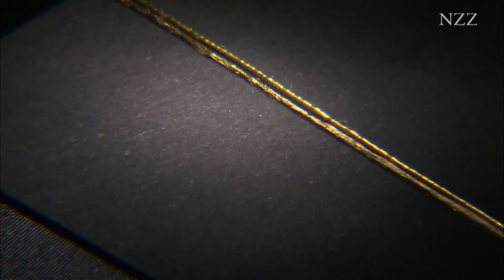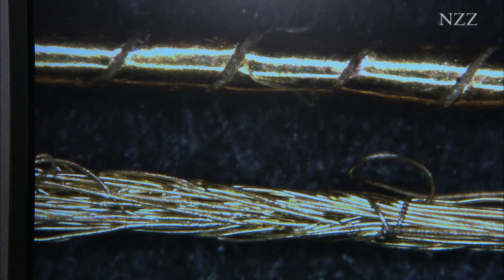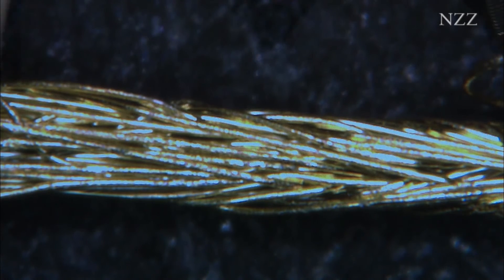The new and the old gold yarn are each one tenth of a millimetre thick. In the picture above you can see the yarn wrapped with gold-plated foil — an old technology used since the Middle Ages, but it scratches the skin and is hard to weave. Below you can see the plasma-coated yarn, which is completely metallised on each fibril, making it very soft and excellent for weaving.